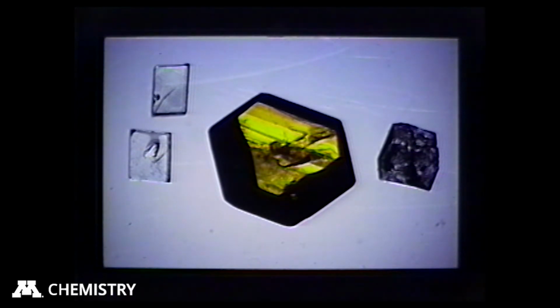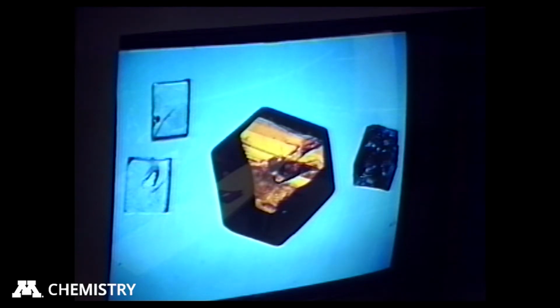All right, these crystals are 3,5-dinitrobenzoic acid. Those crystals grow really well, and I suggest that as a guest molecule if you ever want a guest molecule to promote good crystal growth. This one is a general common system. It has a very acidic proton on it and is useful in many cases where triphenylphosphine oxide doesn't work. On the right is para-aminobenzoic acid, and this is their co-crystal. Now, you also notice you're seeing color develop, and that's because we're using aromatic systems that have donor-acceptor characteristics to them. And when they come into the crystal together, you're getting charge transfer interactions. But we really think it's the hydrogen bonding interactions that are driving these changes.